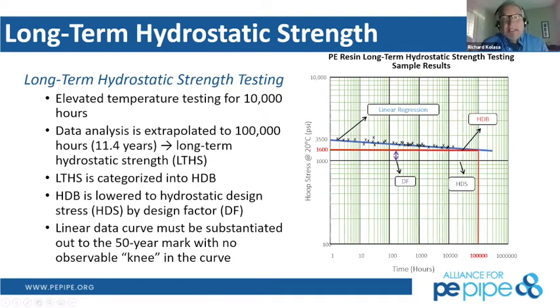Hydrostatic design stress is really depicted here by a log-log relationship between hoop stress and time. And these log-log relationships are very stringent. This process is developed through PPI policy of the Plastics Pipe Institute. The Plastics Pipe Institute has what's called Technical Report 3 that gives the criteria to establish these curves. So negative slope curves, so you can see the blue line with the failure points on them, and those are failure points. And we require failure points in each decade of time in order to create confidence in that data, so we can project either to 11.4 years or even 50 years, depending on the failure mode.